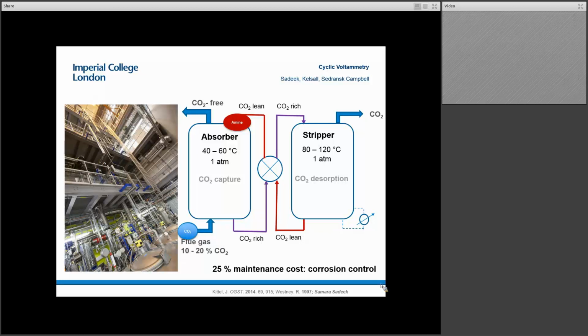So this schematic shows the process, which you can find in post-combustion carbon capture, and actually it's the same technology in natural gas sweetening. But what we're doing here is we introduce a flue gas. It interacts with an amine. The amine then travels from the low temperature region to the high temperature region, where it then releases the CO2, which it had reacted with at the low temperature.